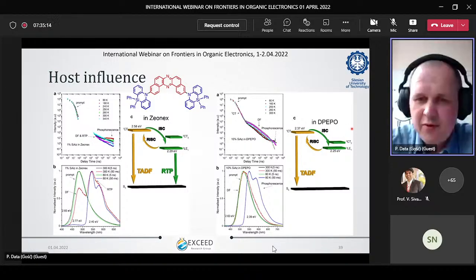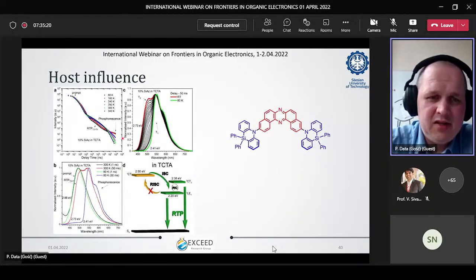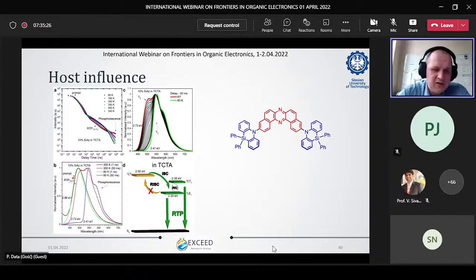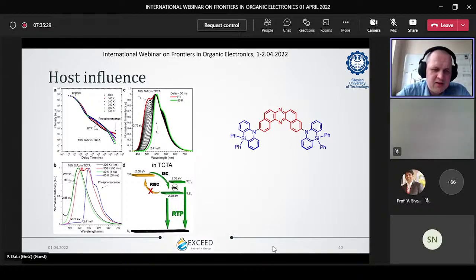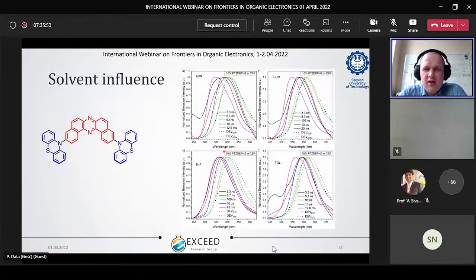If we move to the DPEPO, we had a pure TADF process, very long lived. But in our TCTA, carbazole derivative host, we observe very nice phosphorescence emission, and the phosphorescence from the T2 state. So if you look here, our RISC process was completely closed, forbidden, and we observe emission from two different triplet states by simple host management, by simply checking how it's affecting our molecule.